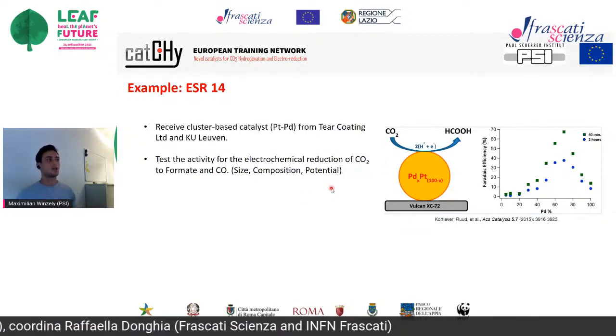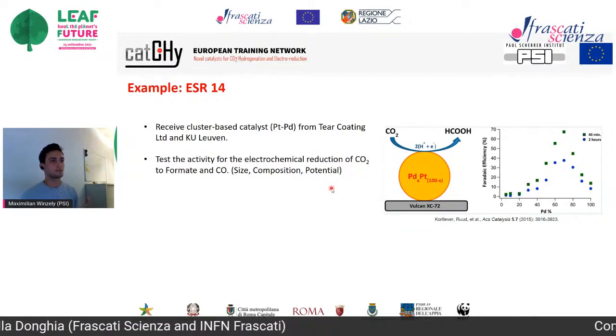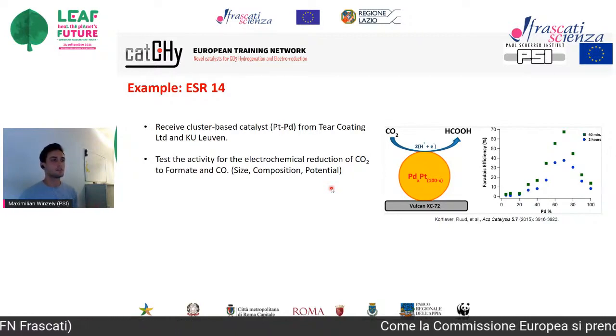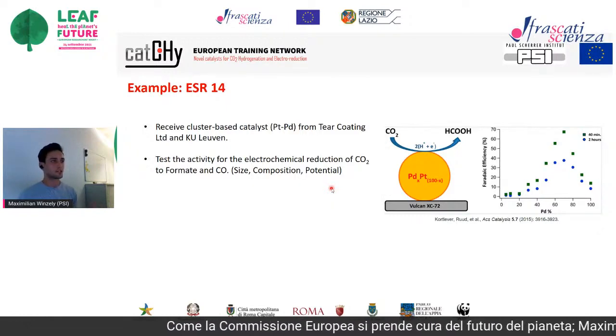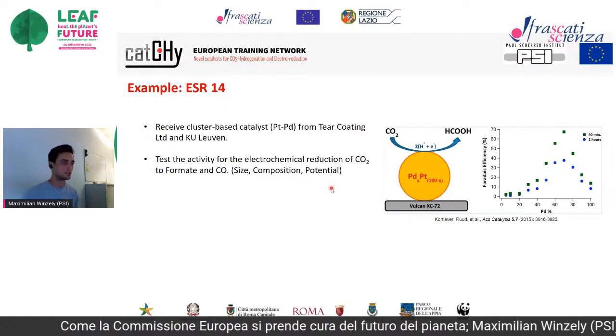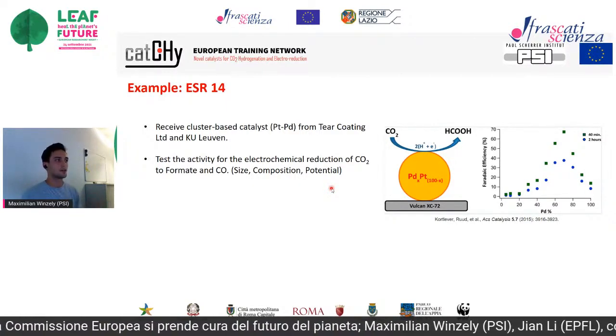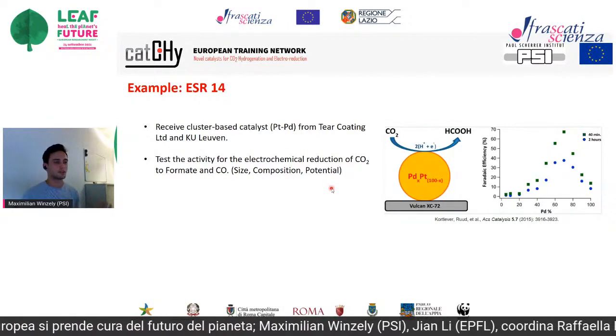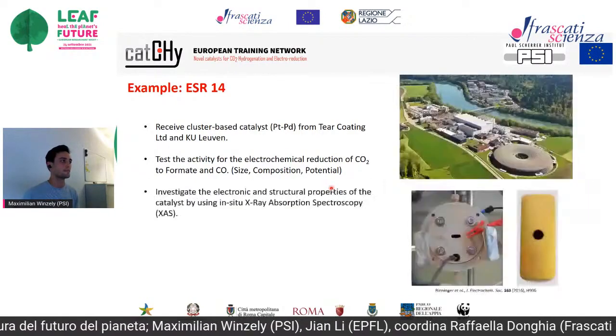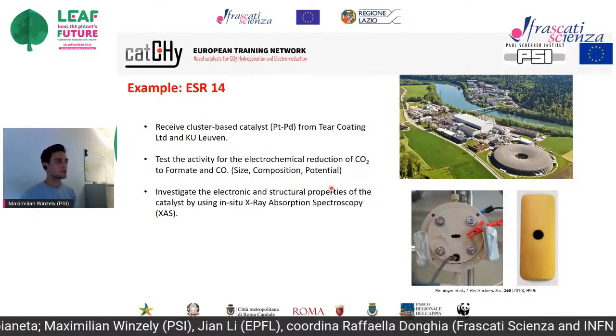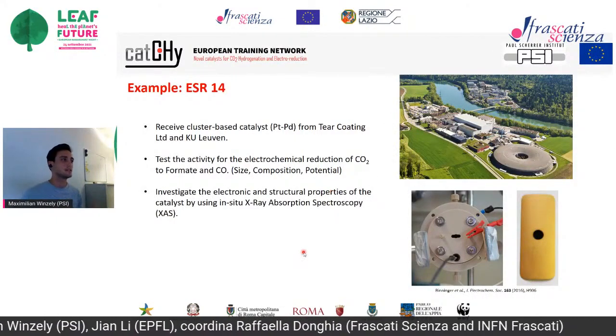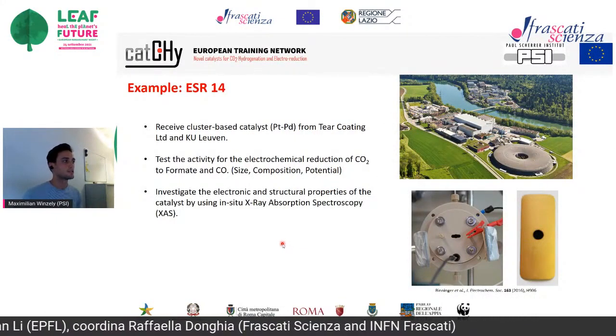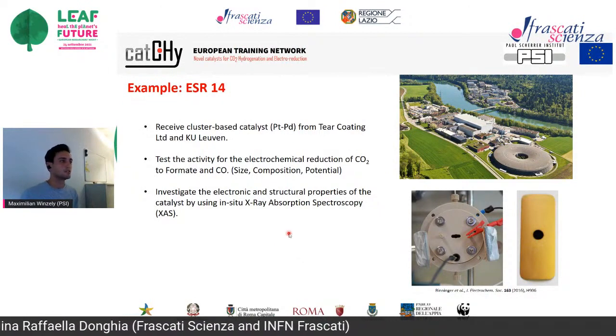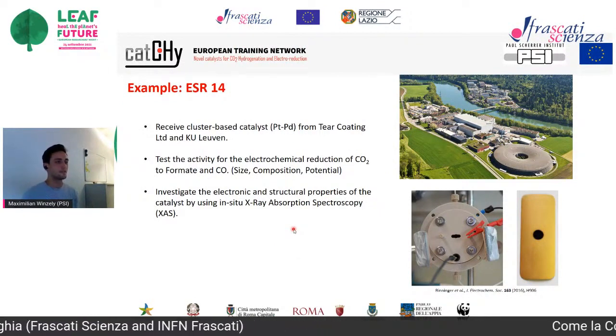And then of course we want to apply different potentials during that electrochemical reduction, because different potentials in electrocatalysis mean that we give different energies for the conversion of CO2. And that can also influence the activity and also, of course, the selectivity. And then what I'm also going to do is to investigate the electronic and structural properties of the catalyst by using in situ X-ray absorption spectroscopy.